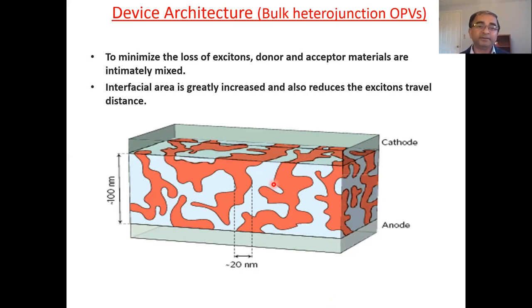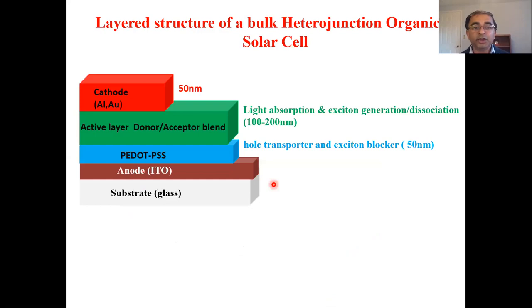Now, this is the basic architecture of a bulk heterojunction solar cell. You have a glass substrate. On that glass substrate, you have ITO as an anode, and then PEDOT:PSS, this is the hole transport layer. It helps in the collection of holes. And this is the actual donor acceptor blend material. This is used for light absorption, and this is the active layer, you can say. And this is a cathode made of aluminum or gold.